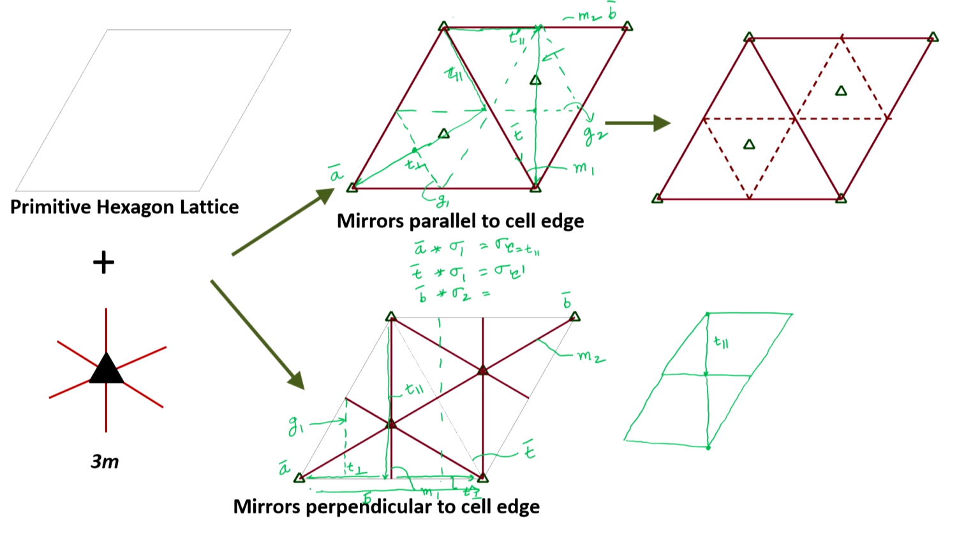So, this is my translation vector B, which I again break up into a parallel component T parallel prime and the perpendicular component, call it T perpendicular double prime, and let me call this T parallel double prime as well. And very clearly I do not have to explain, my glide plane will show up parallel to mirror 2 in this fashion. I think now by symmetry we will be able to replicate all the glide planes that are there,